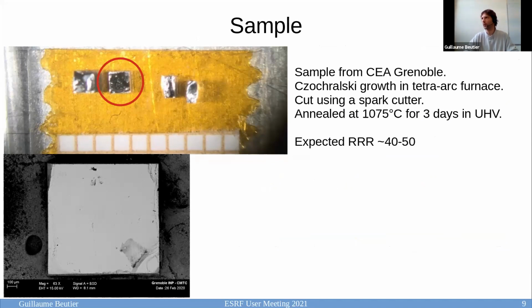and cut using a spark cutter, and then re-anneal for 3 days at an ultra high vacuum. So the group there has a large experience in growing these crystals, and our particular sample was not further characterized in the lab, but based on their experience, they expect that the figure of merit, which is used in this case, which is the triple R coefficient, which is a ratio of resistivity between the room temperature phase and the resistivity at 1.5 Kelvin is around 40 or 50, which is rather good for this kind of growth mode.